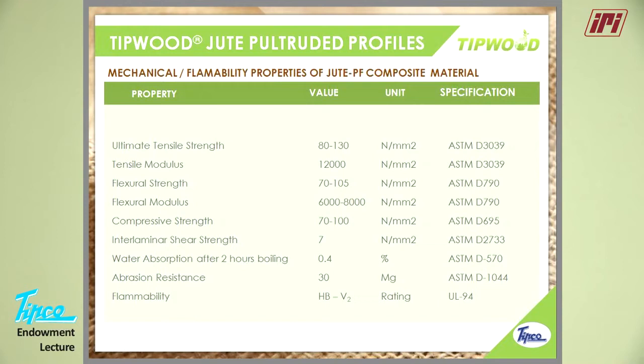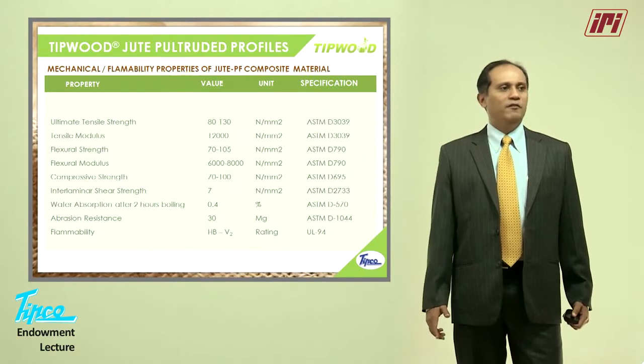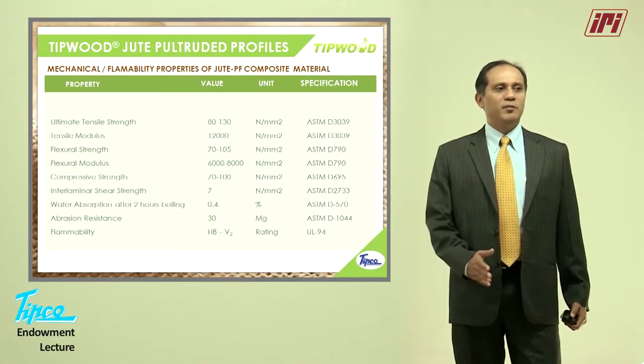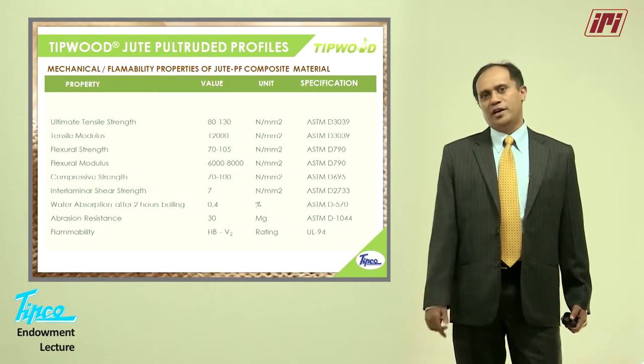Interlaminar shear strength is 7. Water absorption after 2 hours of boiling is only 0.4. When you compare this with normal woods, you will get around 2 to 5% water absorption. Flammability, it ranges from HB to V2 rating from UL 94 standards.